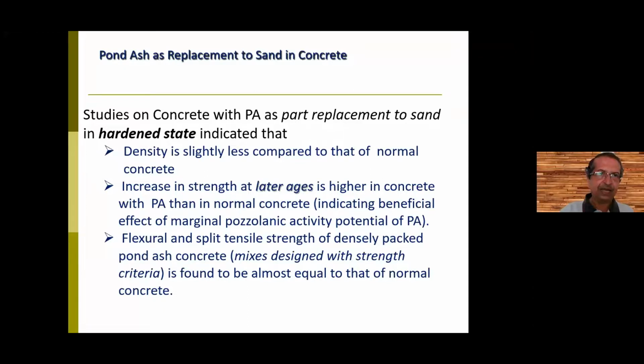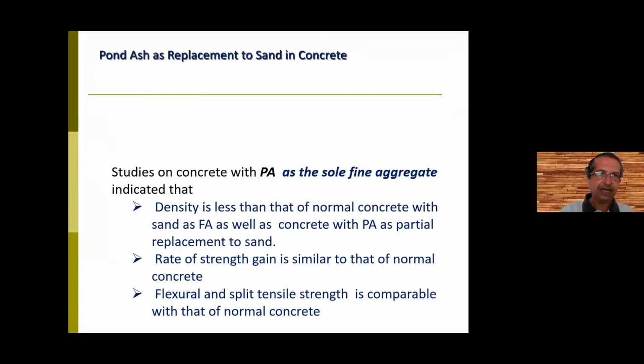And flexural and split tensile strength of densely packed pond ash concrete was found to be equal to that of normal concrete. So, pond ash as a sole aggregate was also tried, and up to M25-30 we could easily make concrete with only pond ash as the fine aggregate. The problem with pond ash we found was that particles between 4.75 and say 1.18 mm are very, very few. The majority of it is less than 1.18.